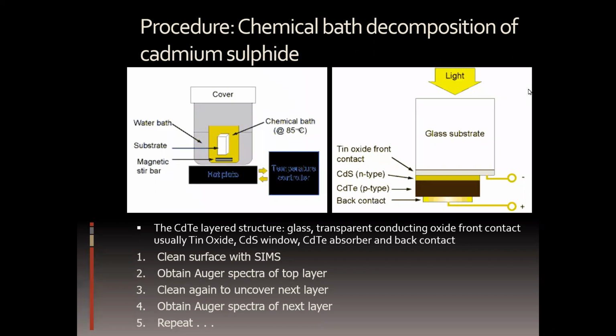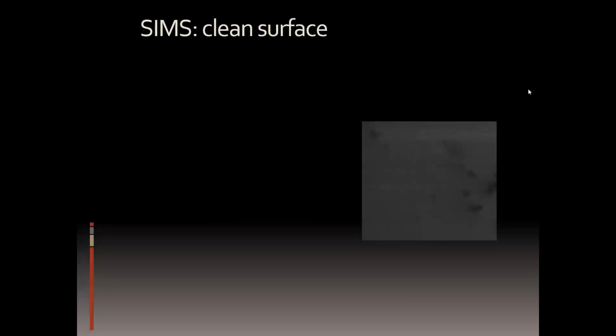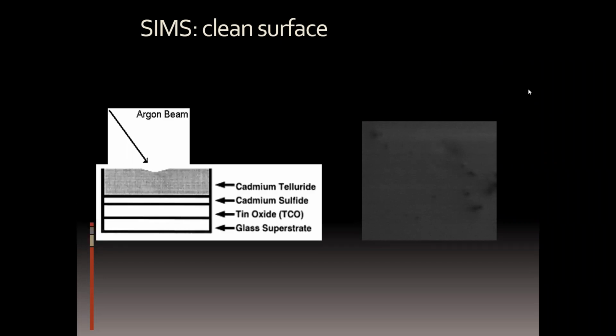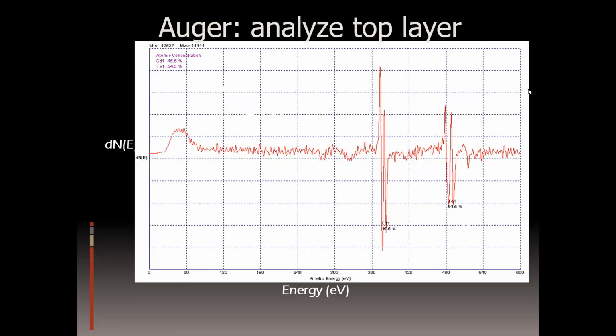We repeat and repeat. So I'm going to show you, this is a map that we did. It has rastering, and you can map the secondary electrons. So the argon beam, and that would be the sample, and the argon would remove part of the upper layer, and then we would do the Auger spectroscopy, and we would get something. Okay, you cannot see this, but this is cadmium, and this is tellurium. Now we're plotting the derivative of the number of counts that we get, which is the usual way to do it. Okay, I'm going to go fast here, but this is one layer.